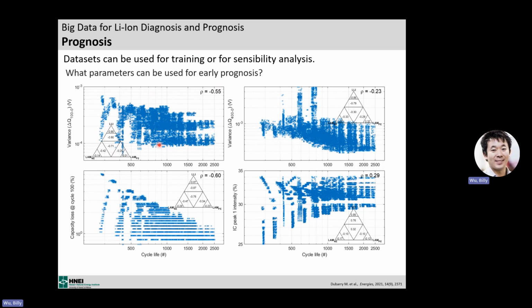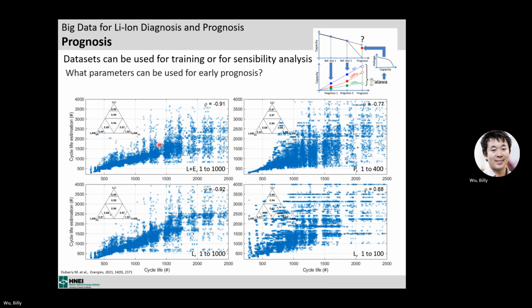So that's to show you one of the benefits of a synthetic data set. Yes, 90% of those might be impossible to get in real life. I absolutely agree. But that's not the point. The point is, here you can test whether or not your method will work on everything or not. And if it doesn't, that gives you some work in terms of design to make sure that those conditions cannot happen in real life. And for us, that's the diagnosis method we have by forecasting the degradation mode. And we can get much better correlation coefficient using that method, using the same data set.